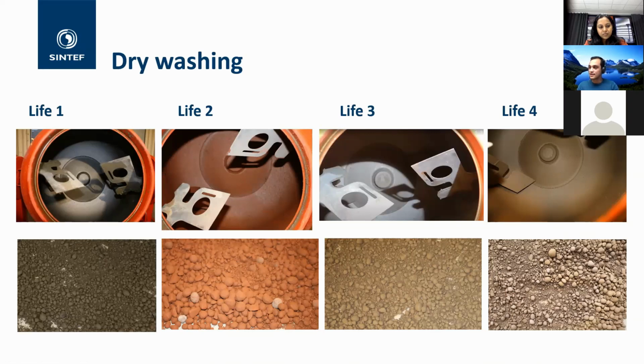Yeah. These are the results from dry cleaning of the concrete drum. As I mentioned, the concrete drum is quite clean, as you can see on the first and third figure, almost shining, and that's without using water. The color on the other two is just because of the pigment. The only downside of this dry cleaning with Recon-Zero powder is the concrete attached to the mixing blades in the drum. Other than that, we have a very small amount of sludge.